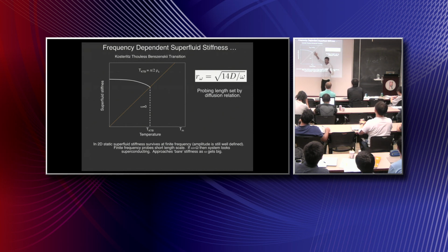This was first shown nicely in mixtures of helium-4, helium-3 films, but is also a general way of understanding superconductivity. So what you would expect, if we plot this dashed line as the Kosterlitz-Thouless condition in some particular units, is that as you warm up your 2D superconductor, the superfluid stiffness would come down until it hits this line, and then there's this catastrophic proliferation of vortex-antivortex pairs, and the superfluid stiffness may just drop to 0. You could imagine another superconductor prepared in some other fashion that would follow a line like this, and then drop to 0. That's if you were measuring at 0 frequency.